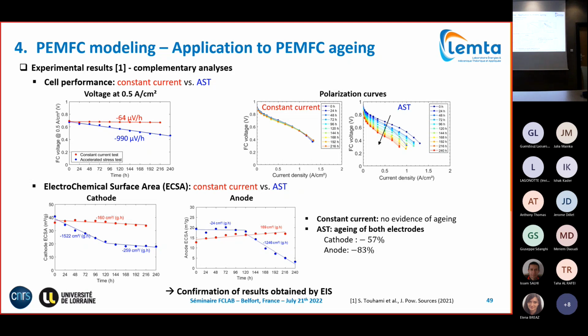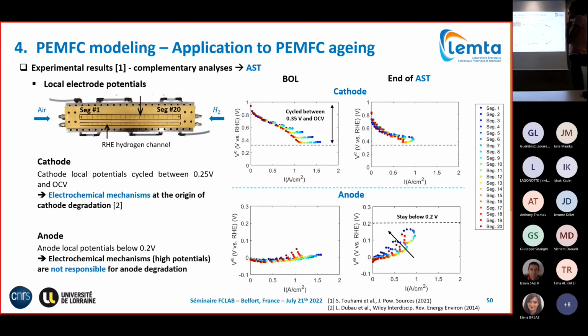Almost no evolution of the electrochemical surface area for the constant current test, but what you see as well here is more surprising: we also had a decrease of the anode electrochemical surface area this time, and much more important than for the cathode. So that's here to say that all our different characterization techniques lead to the same conclusion. Now, what we were interested in was the physical explanation behind this, and therefore what we use is to follow our electrode potentials that we measure thanks to our segmented and instrumented cell, thanks to our reference hydrogen electrodes.